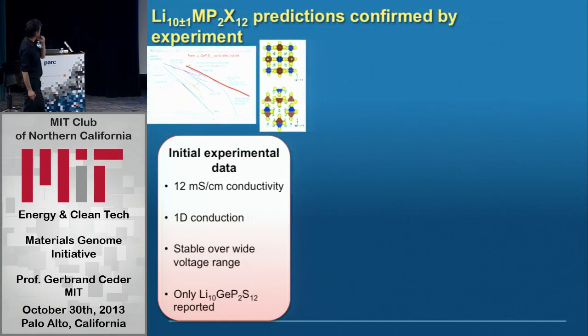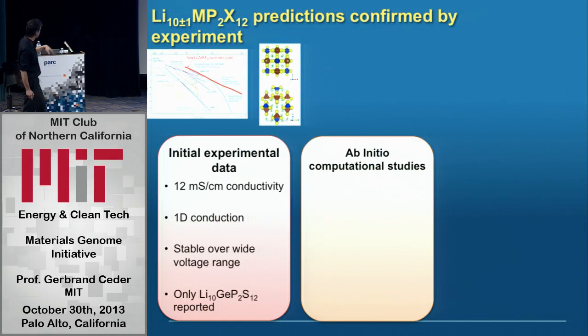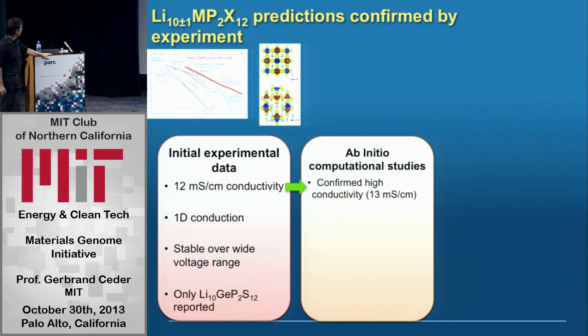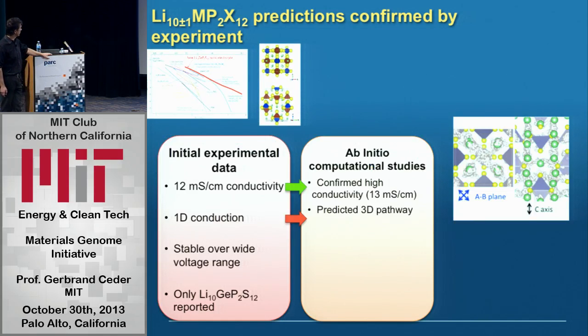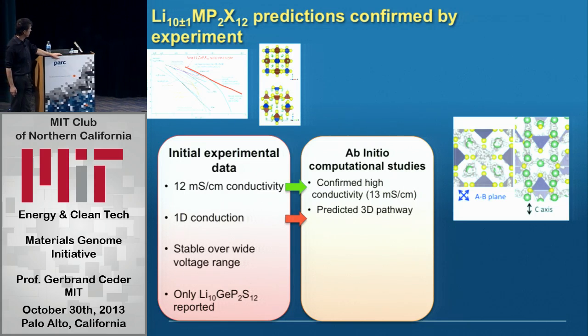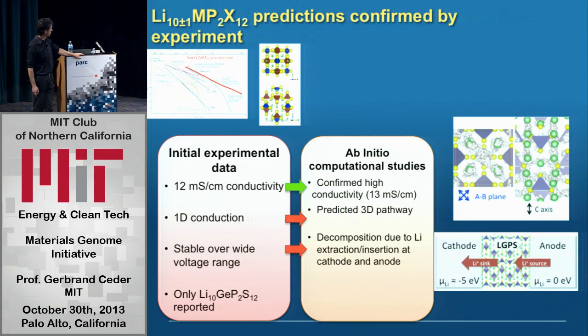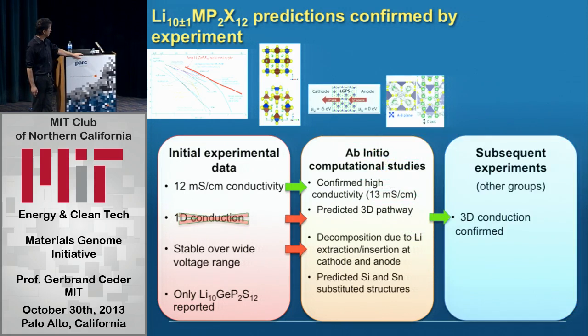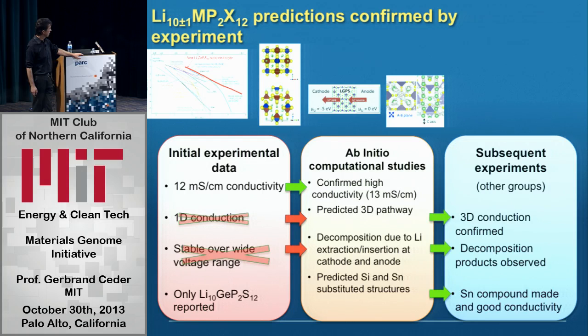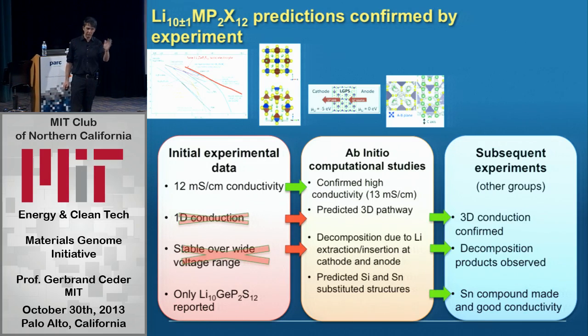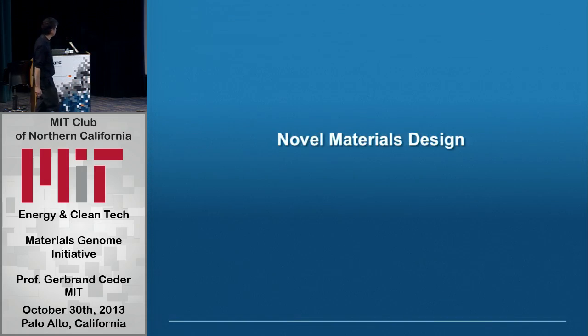So here's how we started in 2011 with the experiments out in the literature. Then we computed, we confirmed the conductivity, we predicted 3D pathways instead of 1D. We predicted decomposition, that's been confirmed. We predicted silicon and tin substitute structures, and at least one of them has been made now. So it's an example of really, think about this, all happened in less than 2 years, right? And the original material came out August 2011. We're 2 years later, and we essentially already have replacements and improved materials for this.